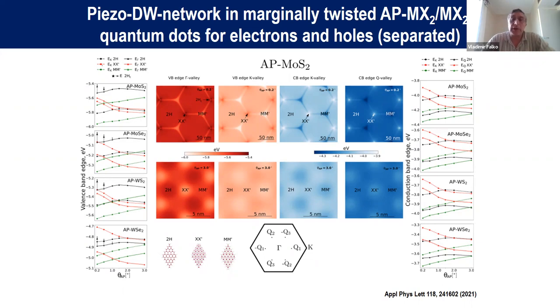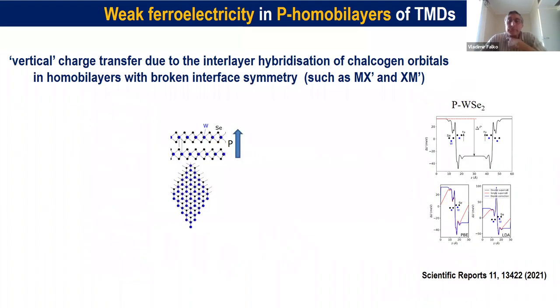So it starts looking like we get a variety of opportunities which can also be tuned, as you can see from the comparison of small angles and large angles, by changing the angle of the twist. Another piece of physics that we came across is the interlayer charge transfer, which we call weak ferroelectric effect. And this comes from the lack of inversion symmetry in the structure with parallel orientation of unit cells of two layers, because both of them don't have inversion symmetry.